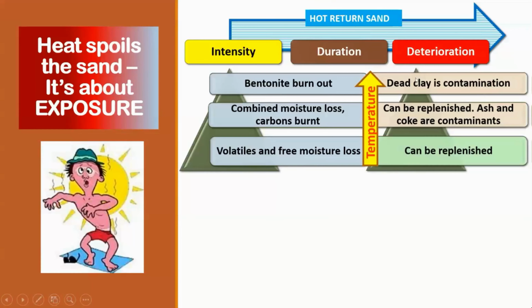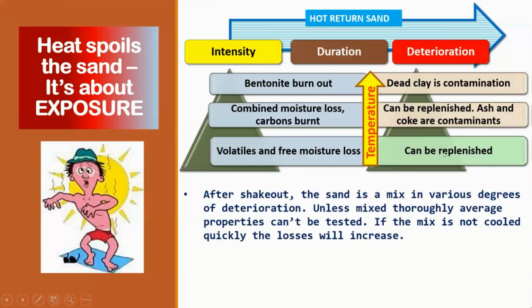So now you need to replenish some part of this dead clay with good clay. You need to replenish the ash, coke contents which are coming out of carbons. So you replace the carbons. You can put some more moisture to get it back to its green state. So after the shakeout, the sand is a mix in various degrees of deterioration. Unless mixed thoroughly, average properties can't be tested. If the mix is not cooled quickly, the losses will increase.